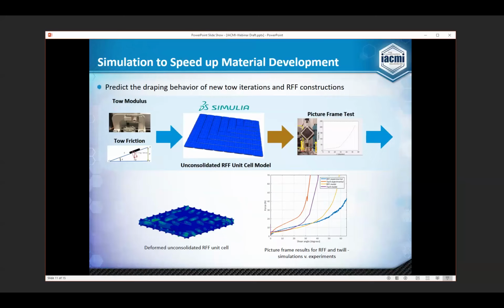So we're able to go from our measurements for the modulus of the tow, the friction between tows and between a tow and a molding surface, and use that to model how our material behaves, and use that for when we want to change fiber volume fractions, change sizes of our tows, if we want to go from a 12K tow to a higher count, those types of things we can explore computationally.